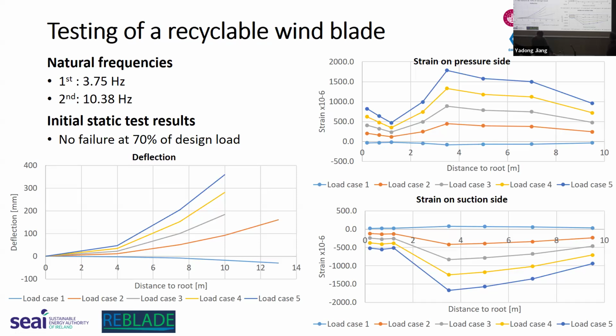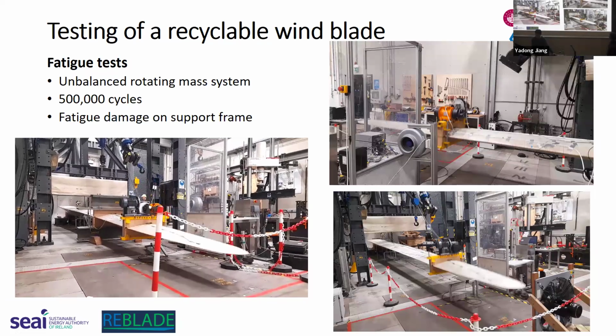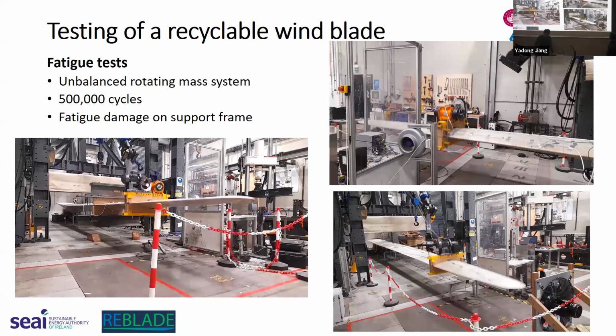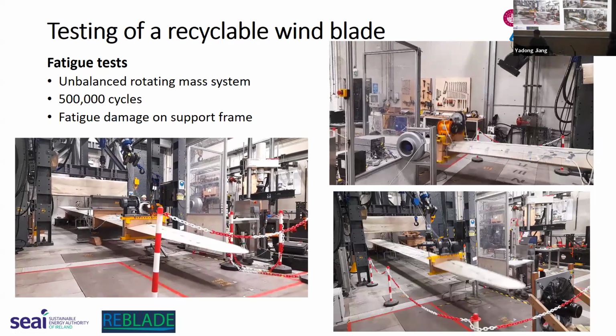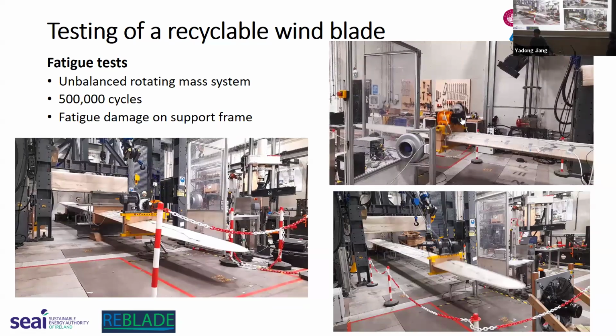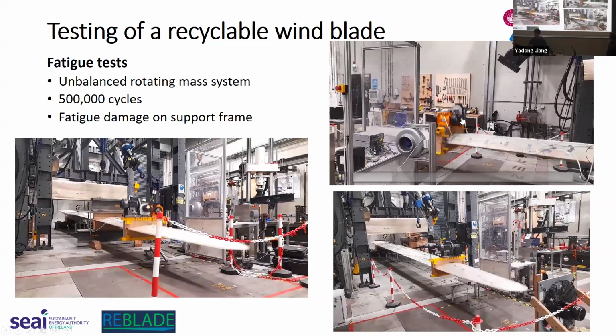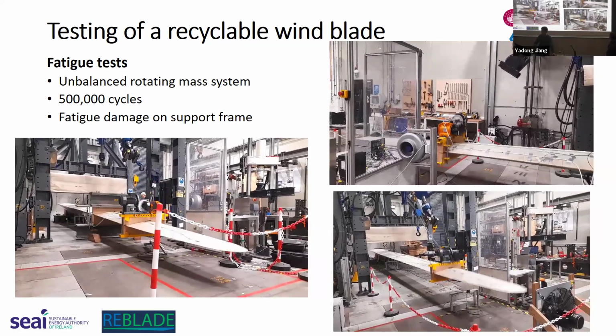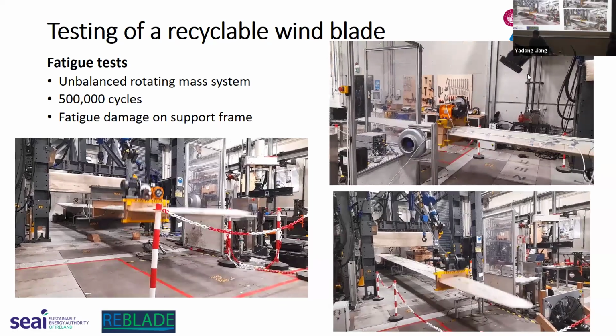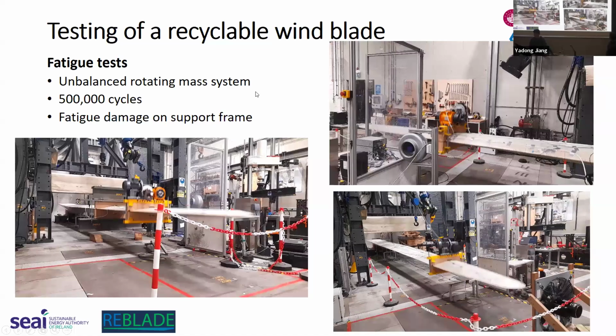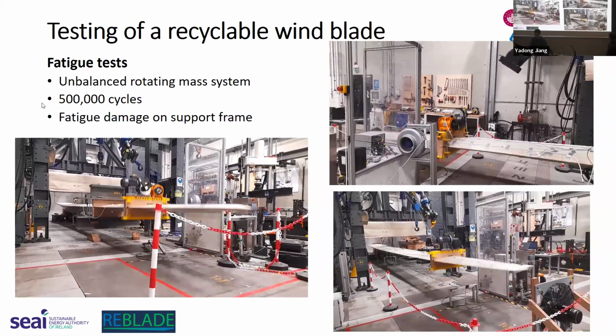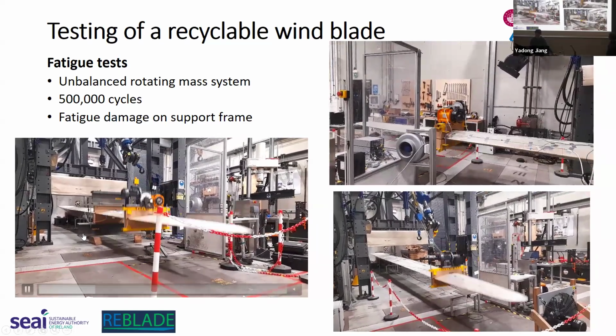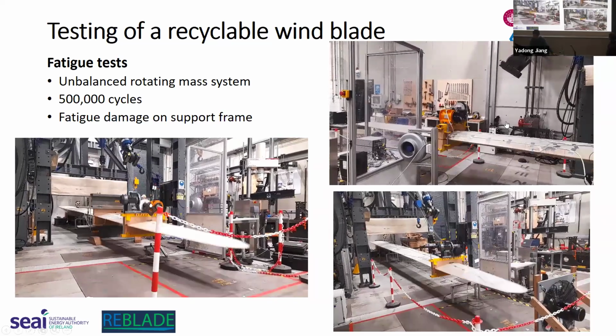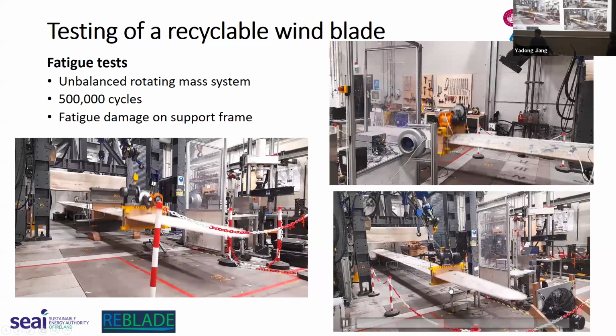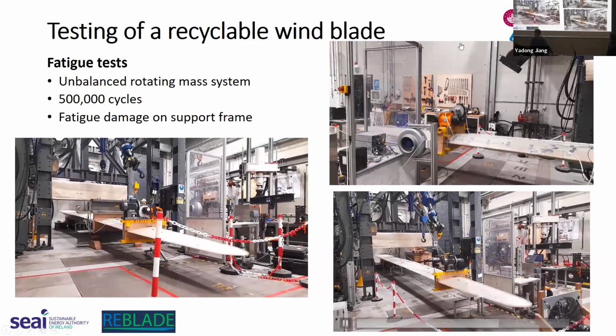And then we can continue with the fatigue test. For the fatigue test, we tried different load mechanisms to simulate the working conditions. We used an electric motor to rotate, and on the motor there is an unbalanced mass system. When it rotates, it generates vibrations up and down and makes the blade vibrate. Here I show 3 different setups, and each represents one fatigue load condition. For this one, we have 2 electric motors and a mass mounted at the middle of the blade, and it vibrated a little bit smaller than the other one. For these 2, there is no mass attached to the blade, only the rotor. Here is a single rotor, and here is a different rotor.